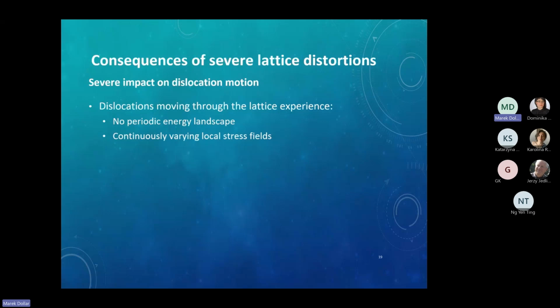lattice, as energy landscape changes tremendously. Because if we have one element, essentially, and this dislocation moves, it follows a sine function. It kind of moves from one type of spaces to another in a way requiring very little energy. But that's not what we have here. And the local, each additional element, the presence of the dislocation in proximity to these elements leads to strong local fields, strain fields.